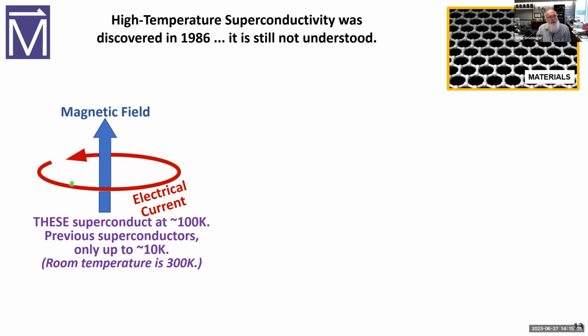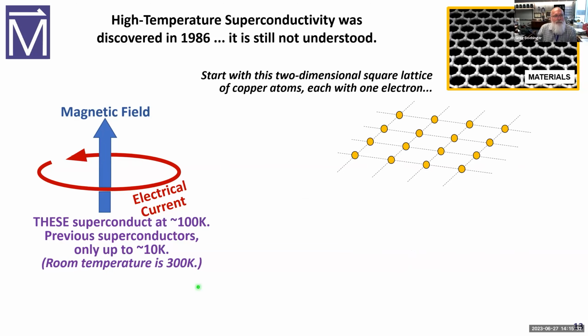And the reason we call these high-temperature superconductors is that when we make a coil into which we put an electrical current out of these materials, they superconduct with no friction at about 100 Kelvin, whereas previous superconductors only went up to about 10 Kelvin. And room temperature is 300 Kelvin. So this leap was a huge step towards room temperature superconductivity.